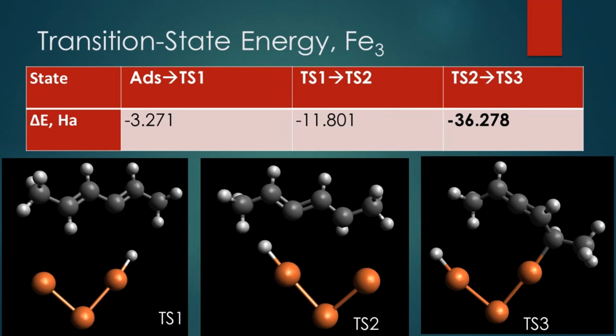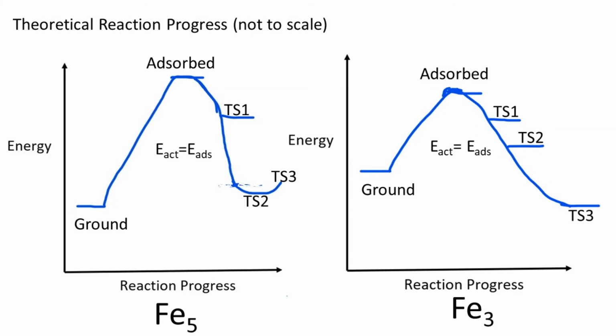The iron 3 surface has an equally interesting result. After adsorption, the energy decreases by more and more each step until it settles on TS3, where the carbon radical formed a bond with the open iron atom. It appears that the formation of the iron-carbon bond is enough on its own to pay back the energy of adsorption. In the iron 5 case, on the other hand, the iron prefers to stay in transition state 2, which gives the carbon radical the chance to initiate cross-polymerization.